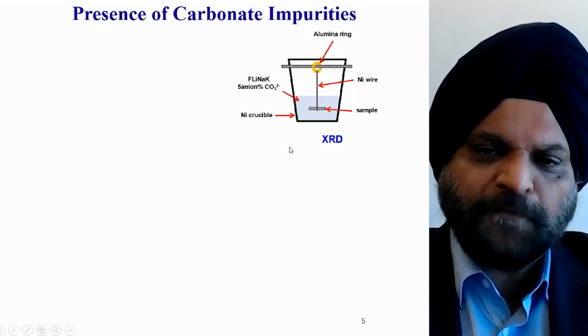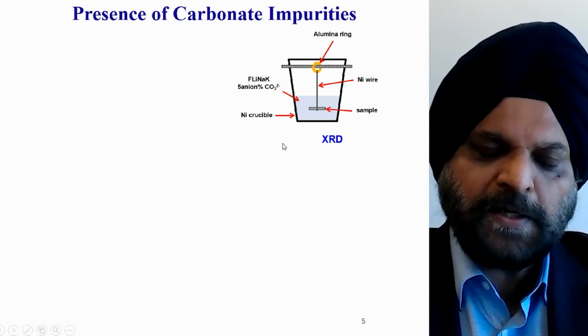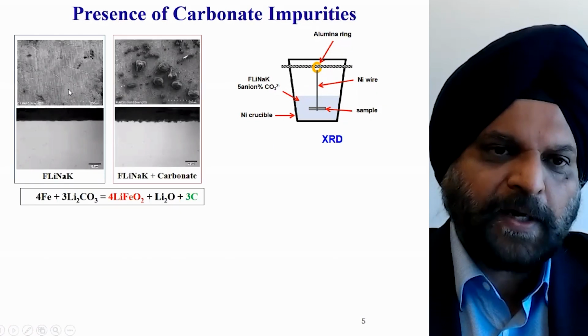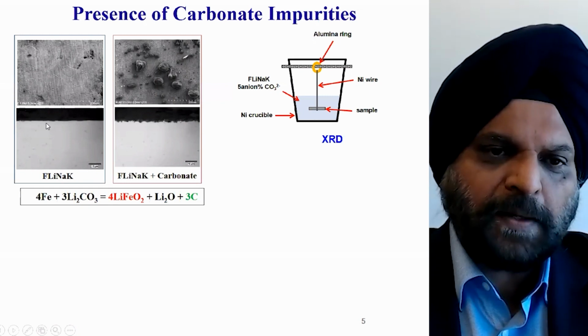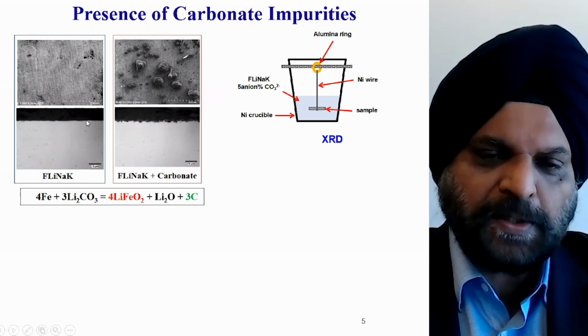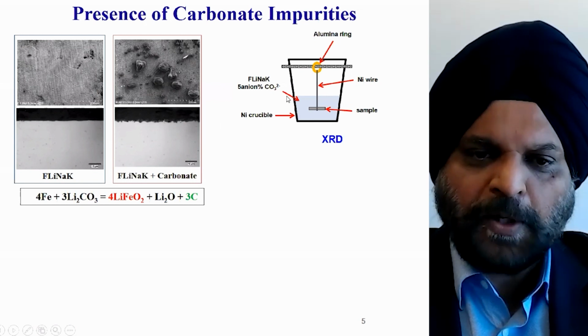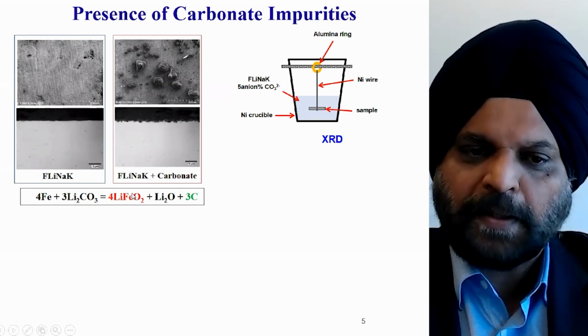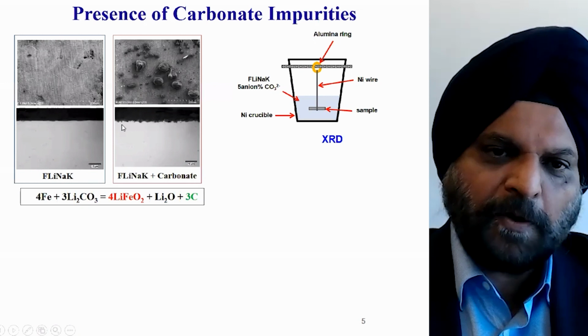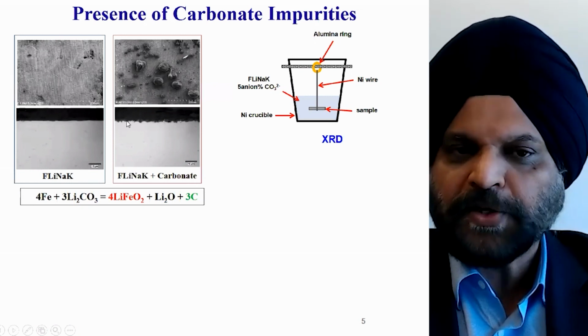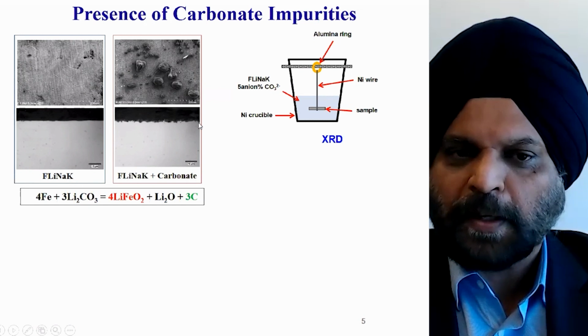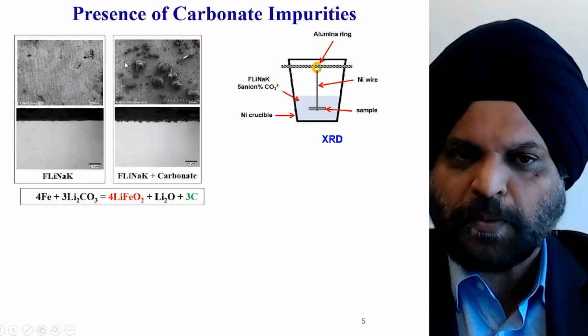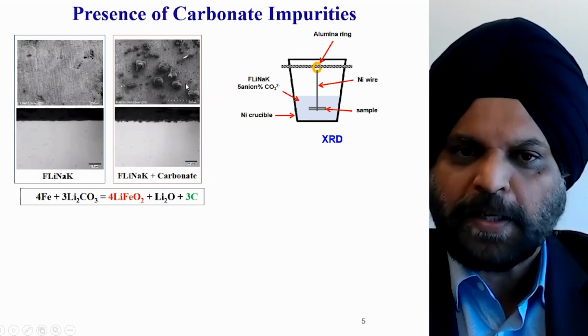What we found is that if you do tests without any carbonate, just in FLiNaK, on the left-hand side you have some intergranular attack on the surface, but a mostly smooth cross-section. Now, if you add carbonate, you can have this reaction where lithium carbonate reacts with iron, giving you lithium iron oxide and carbon at the surface. When we section that type of exposed sample, we see a carbon layer at the surface. And in SEM at the surface, there are discrete particles.